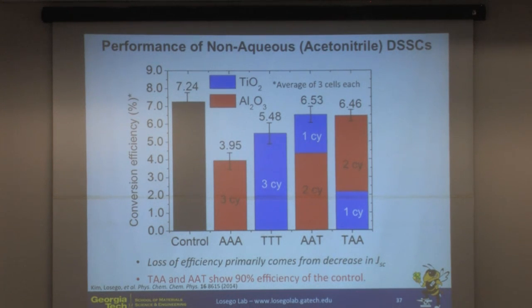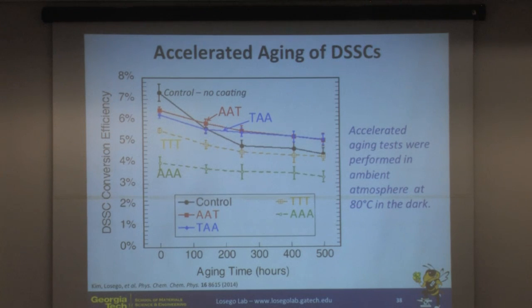So now we're pretty close to where we were. And if we look at the efficiency as we age these devices, this is a standard aging test where we do 80 degrees C in the dark, so in an oven at 80 degrees C. And this is again what I'll point out here: oftentimes people will normalize these sorts of plots. We're not normalizing this data here. This is actual efficiency of the devices.